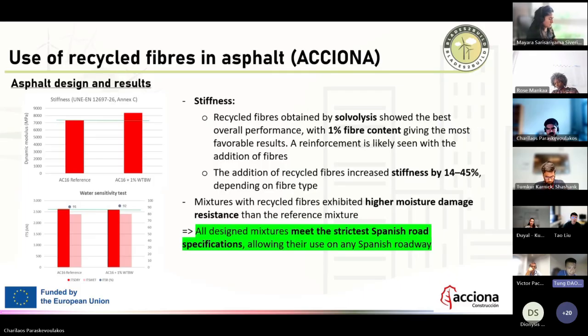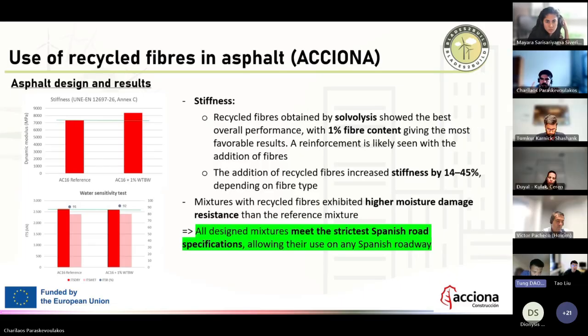So in a few words, they have a set of samples that they conserve in the air, in controlled conditions, and a second set of samples that they put under the water, and then they take them out after 7 days or 28 days, and they do the compressive strength, or I don't know what kind of test here, and then they compare. If the asphalt is in the air conservation condition or in the water conservation condition, what is the difference? And we see that yes, because of the water conservation, the mechanical behavior of the asphalt is reduced, but compared to the ordinary asphalt, where there was 9% loss in terms of strength, in the new recipe with 1% of clean recycled fibers from the wind turbine blade waste, the loss is around 8%.